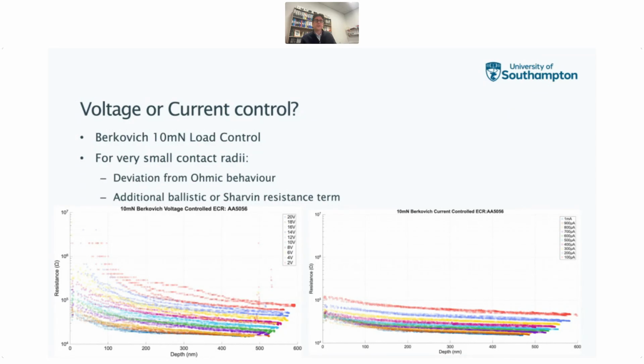You can see the response in current control is a lot more linear compared to voltage control. So we generally proceeded with current control for these types of measurements. But the other thing I wanted to point out was that, depending on the amount of power you're putting in here, we were getting a difference in the maximum depth of penetration at the 10 millinewtons. You notice there's a bit of a curve up here on both graphs, going from the low voltage to the high voltage, or the low current to the high current. And we were getting higher penetration depths for the lower power that was being applied.